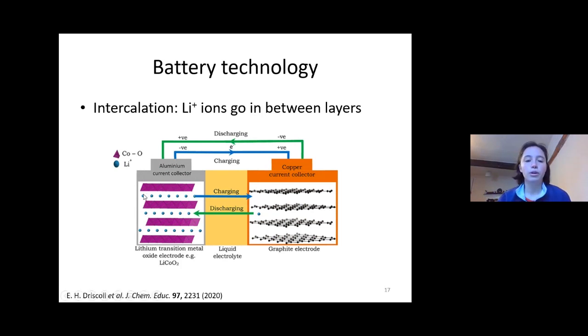So if you look at the cathode, which is on the left, we've got the purple layers are cobalt and oxygen, and the lithium plus are the blue spheres in between. As we charge the battery, those ions get taken out from in between the layers, and they move through the electrolyte, and they go in between the layers on the right-hand side in the graphite electrode, the anode.